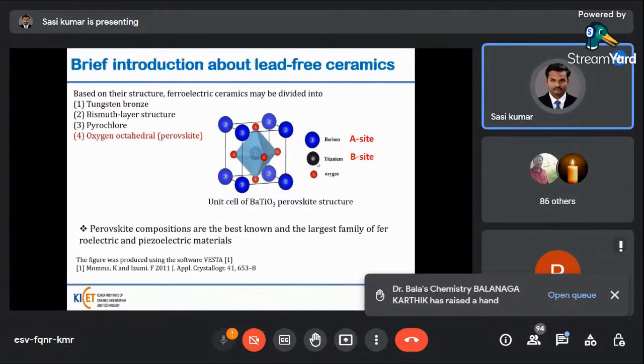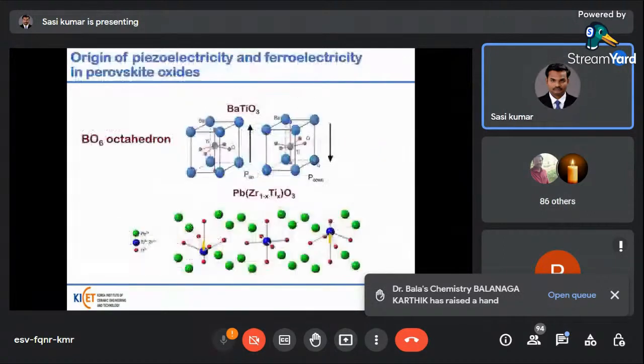It is developed by many researchers. The origin of piezoelectricity and ferroelectricity in perovskite oxide mainly depends on the BO6 octahedron, where B is the B-site center atom. The vibration of the Ti-O bonding mainly causes the piezoelectric and ferroelectric properties in perovskite oxide materials. BaTiO3 and lead zirconium titanate oxide are some of the main examples of perovskite oxides.